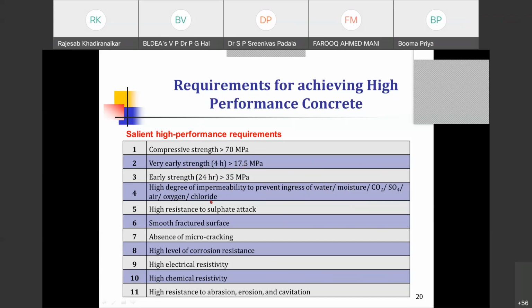Then a high degree of impermeability, preventing ingress of water, moisture, carbon dioxide, sulfur oxides, air, oxygen, chloride. This depends on the permeability of concrete. High resistance to sulfate attack. This is chemical attack. Smooth fractured surfaces. Then absence of micro cracking. In conventional concrete, you have a lot of micro cracking because of higher water cement ratio. So the absence of micro cracking is there. Then a high level of corrosion resistance.